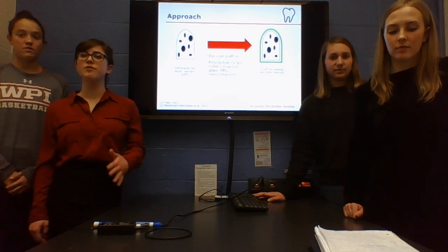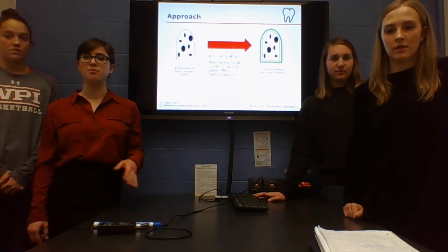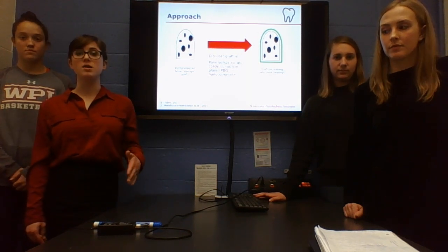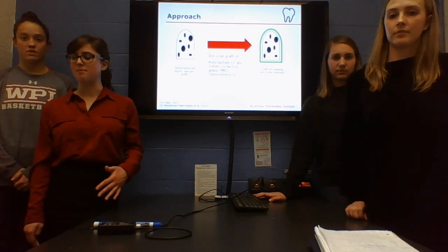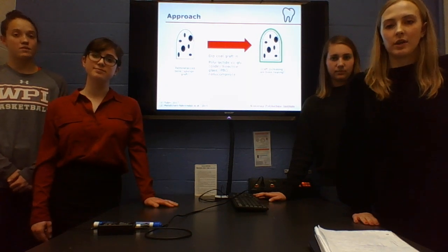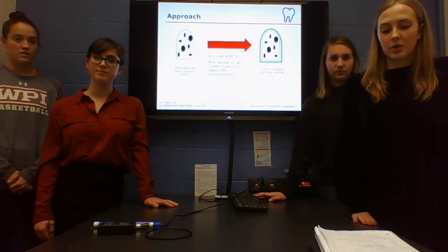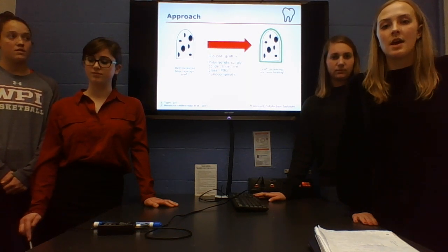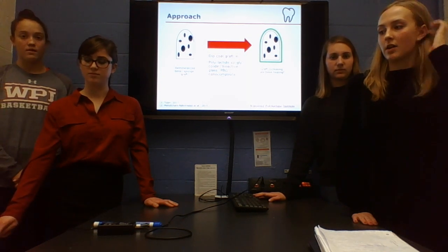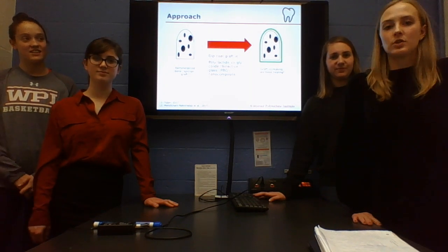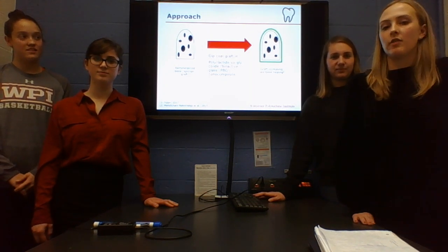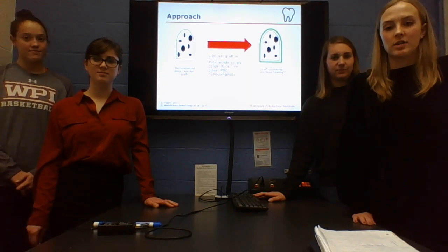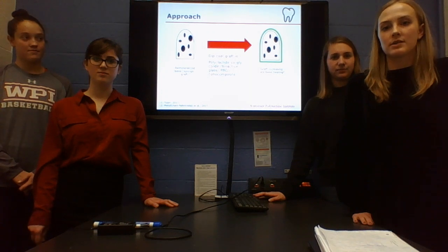So the basis of our design would be using a demineralized bone sponge graft. This on its own would take a long time to heal, so we plan on improving upon this by adding a coating. The coating that we plan on adding is a polylactide coglycolide with bioactive glass, and it's in the form of a nanocomposite, and this will be dip coated onto the graft. This was chosen because it increases the rate of bone healing and osseointegration, and also has less wear debris than hydroxyapatite, which is commonly used in Bio-Oss.